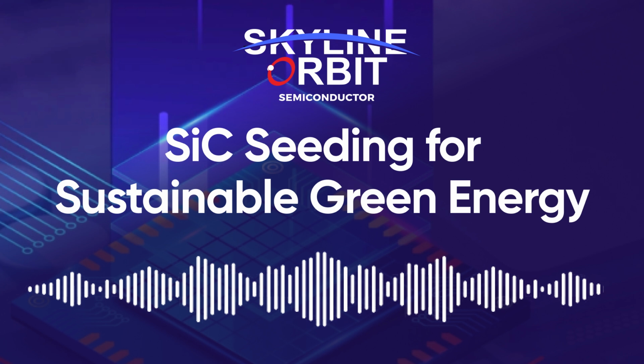Can you walk us through how it actually works? I mean, it sounds pretty complex. Yeah, it is. It's actually pretty cool. So you start with super pure SiC powder, and they put it in a special crucible inside a furnace, and they crank up the heat, like way up, over 2,000 degrees C. Now, at the top of the growth chamber, there's this really carefully cut piece of SiC single crystal, called the seed crystal. So inside this carefully controlled low-pressure environment, the SiC powder actually undergoes sublimation. It goes straight from a solid to a gas.